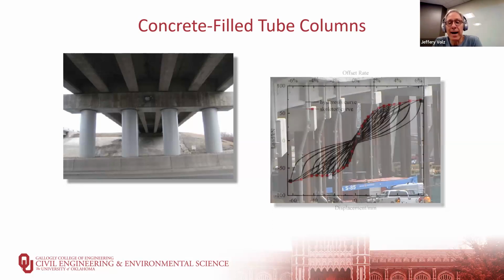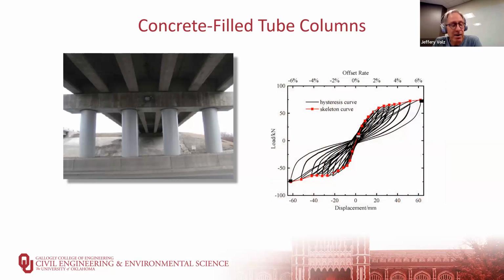If we look at the load deflection plot, same kind of specimen, fixed at the base, constant axial load, increasing lateral load, we get a very good hysteresis loop. It is a very stable hysteresis loop, which is important. And the column has reached a ductility ratio or drift ratio of 6% before it failed.